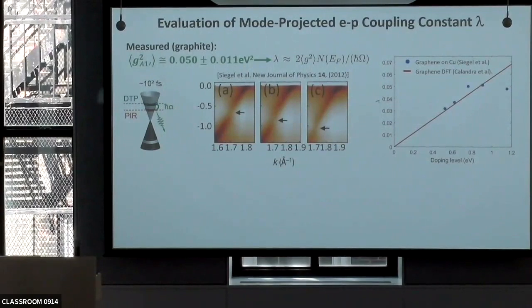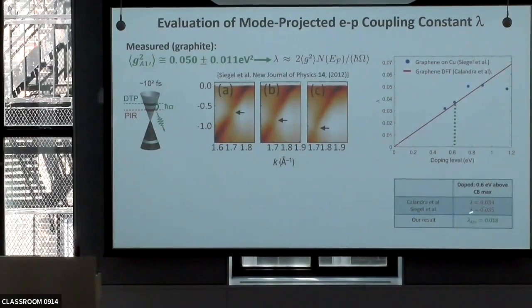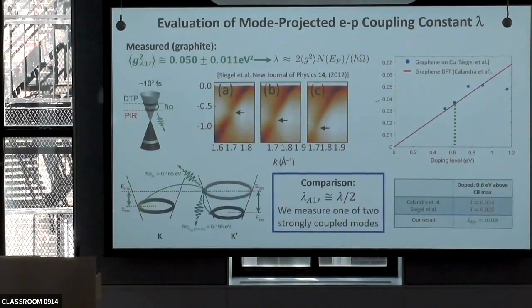So we go back to the graphene case. See the data that were obtained basically by Lanzara's group, with a DFT estimate that was in agreement. The two numbers you get at this particular value, which is where we are, 0.6 eV above the chemical potential, are in the range of 0.034 for a lambda. And when we calculate our lambda, it is about a factor of 2 less. It's comparable, but a factor of 2 less. This is interesting because, as I was showing before, there are two possible mechanisms for decaying here, but the one we have measured is this single one. While in this kind of analysis, you're integrating over all possible ones, so you're looking not only at the K phonons but also the gamma phonons, and that would explain why our number is roughly a factor of 2 off from what's seen with the other approach.